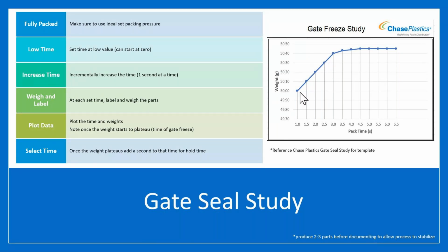So what we see here is our gate's still not frozen here because we were able to add a 1/10 of a gram, another 1/10 of a gram, gate's still not frozen. We're packing it 2.5 seconds now. We can still get another 1/10 of a gram in there. Part weight is still increasing. That means that flow channel, the gate, is still molten and open. You'll notice at about 4.5 seconds here on this particular curve, we can no longer affect the part weight with more packing time. That's a great indication that that gate is solidified because we can no longer adjust what's happening past it.